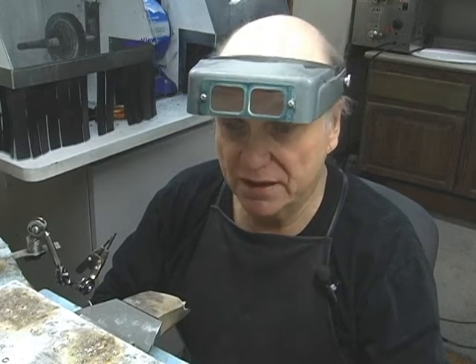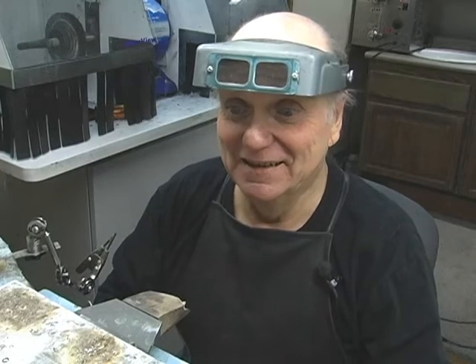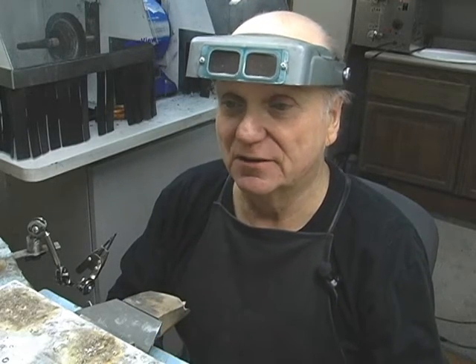Silver, if it has any stones, can be difficult to work on. Never ever solder a ring that's silver that has anything glued into it. You're going to pop it no matter what precautions you take. So do not, I repeat, do not work on anything that has stones glued in when it comes to silver. Again, I know, I did it years and years ago. The other thing is, when you do have stones in it, what it is about silver is the heat transference. Silver loves to be as hot everywhere as it is where the torch is. So if you have stones in it, the stones are going to burn up.